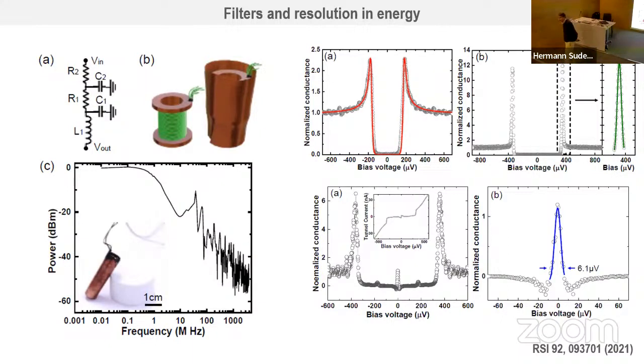Yeah, could it be that you don't have enough resolution in the STM to see the tiny structural charge density waves that might appear, or is this completely excluded? Well, with an STM you can make the Fourier transform and you see the Bragg peaks. Now, with X-rays, you see the Fourier transform of 10^23 atoms. So you have a resolution which is far better than with STM. Now, people have been looking at this problem with X-rays, of course, and sometimes they see a little change of 10^-5 in the lattice constant difference between a and b. But it's probably due to impurities.